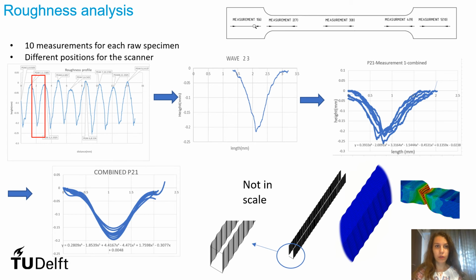The roughness of the material is a really important parameter that was crucial to our research. Even though first time we measured each and every raw specimen with a caliper, because we knew that roughness is going to be of crucial importance, we decided to scan with a 3D scanner all the raw specimens. For each raw specimen, 10 measurements were made, like in the picture in the top right corner, 5 measurements on one side of the specimen and 5 on the other side of the specimen.